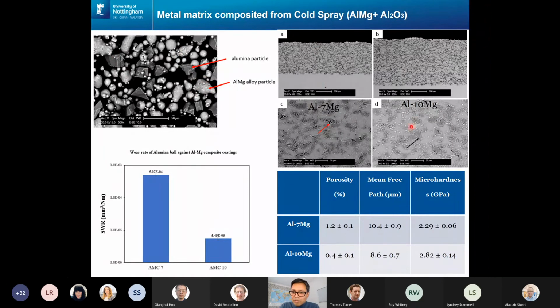So there are two sets of examples here. One is an aluminum 7 magnesium weight percent. Another one here is aluminum 10 magnesium. The darker phase, that's the coating microstructure here, and that's the substrate. The darker phase here is ceramic and the brighter one is metallic. And you can see the uniform distribution of these structures. By using cold spray, we can reduce the porosity of these MMCs to around 1%. So they are really dense, useful MMCs for lots of applications.